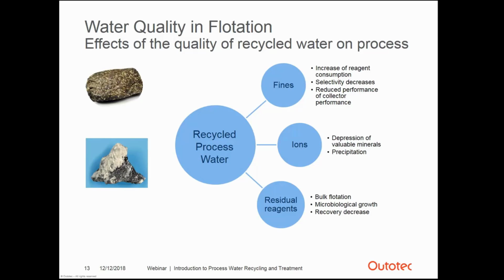So what we know about the impact of fines in recycled water is that they have a large surface area, which increases flotation chemical consumption. Also, selectivity tends to decrease with the increase of fines. In some cases, fines with opposite surface potential will attach to valuable mineral surfaces and this way prevent collectors from attaching. Then ions, we know that some ions can depress or adhere on the surface of valuable mineral and this way prevent adsorption of collector on the surface of mineral particles.